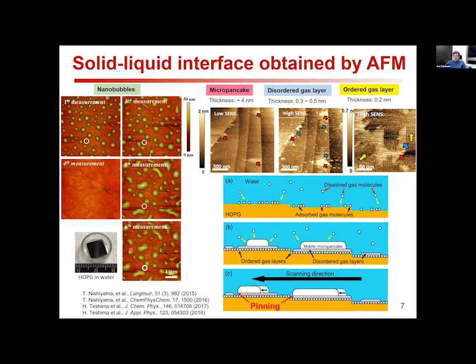This slide shows AFM images obtained by our group, especially the very tiny and nanoscale gas phases. The biggest one is the nanobubbles at the liquid water graphite interface. And the next ones are micropancakes and disordered and ordered gas layers. These 4 types of gas phases have been found. For example, this ordered gas layer consists of air molecules aligned epitaxially on the carbon atoms of the graphite surface. We first found this micropancake can move, but is pinned at the edge of lower layers. This is a very important finding to understand the phase change phenomena.